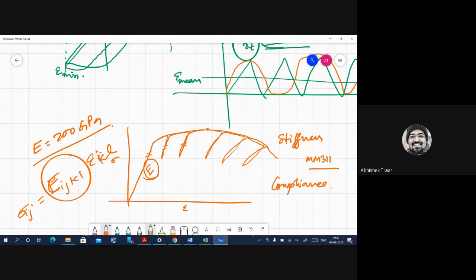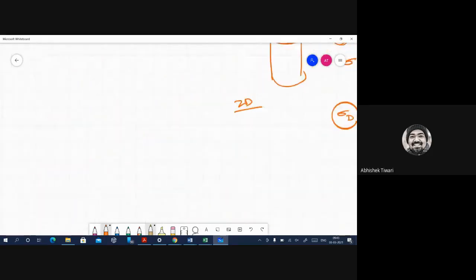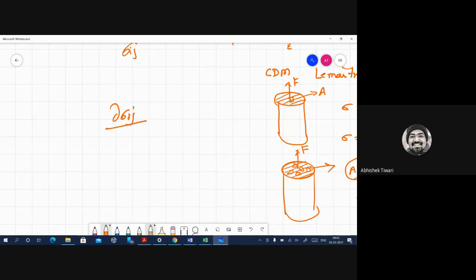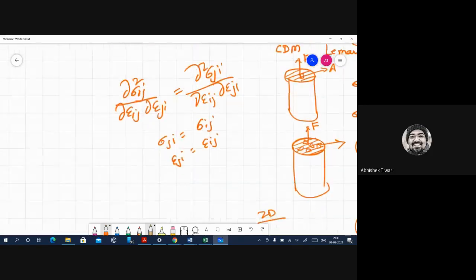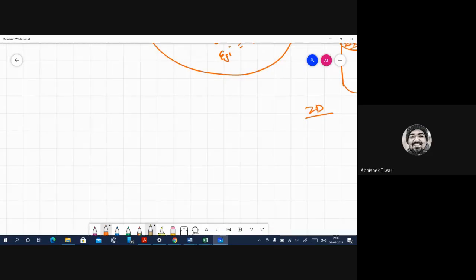And if you remember, if you do not apply symmetry and strain compatibility and equilibrium forces, then you should have 81 components. And when you reduce it by applying different conditions, we proved that delta sigma ij divided by delta epsilon ij into delta epsilon ji is equal to delta sigma ji divided by delta epsilon ij delta epsilon ji. Also, we proved that sigma ji is equal to sigma ij and epsilon ji is equal to epsilon ij because of symmetry, right? So using all these criteria, we reduced 81 components to basically 2 components in an isotropic material. And it has to be isotropic to get this reduction. And that is elastic modulus basically and Poisson's ratio.